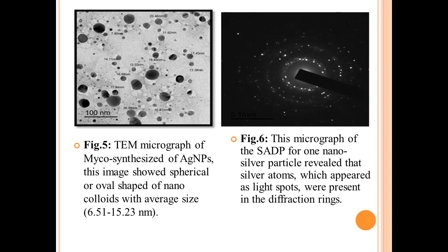Figure 5, TEM micrograph of mycosynthesized silver nanoparticles. This image shows spherical or oval-shaped nanocolloids with average size 6 to 15 nanometers. Figure 6, this micrograph of the selected area diffraction pattern for silver nanoparticles revealed that silver atoms, which appeared as light spots, were present in the diffraction ring.